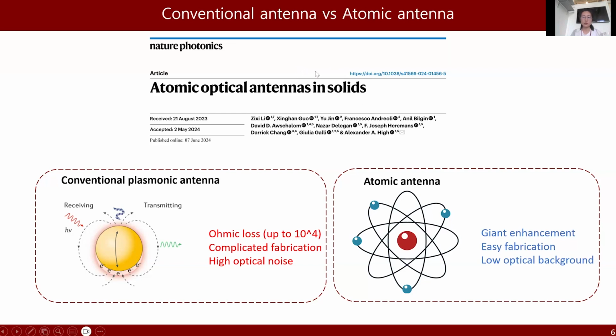And in this new work that we published 1 month ago, we investigated a new type of antenna called the atomic antenna. The principle of the atomic antenna is very similar to the plasmonic antenna. The electron of an atomic dipole will oscillate when it transitions between a ground state and an optically excited state and concentrate a huge amount of energy. This makes those atomic dipoles excellent antennas. And since it's just single atoms, it does not have ohmic loss. So in principle, it's loss-free and it should have a very huge near-field enhancement.